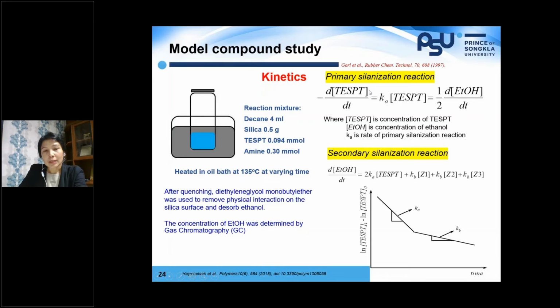Once we have the silanization reaction, we have a byproduct of ethanol. So first of all, we study the kinetics of those different amines on the silanization reaction. The model compound study was based on a mixture of decane with silica and silane, and we have amine heated at 135, and then we follow this procedure, and we want to measure the concentration of ethanol. So we did that by using GC.